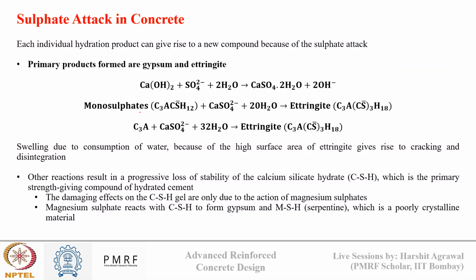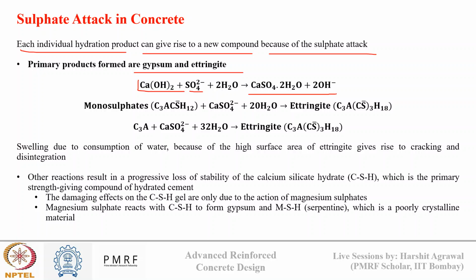So basically, each individual hydration product can give rise to a new compound because of sulfate attack. Okay, now the primary products that result from sulfate attack are gypsum and ettringite. In the first reaction you can see CH is reacting with sulfates to form gypsum. And in the second and the third reaction you can see this ettringite formation occurring when sulfate reacts with monosulfates and C3A. So you can see these are sulfates reacting with monosulfates and calcium aluminates to form ettringite.